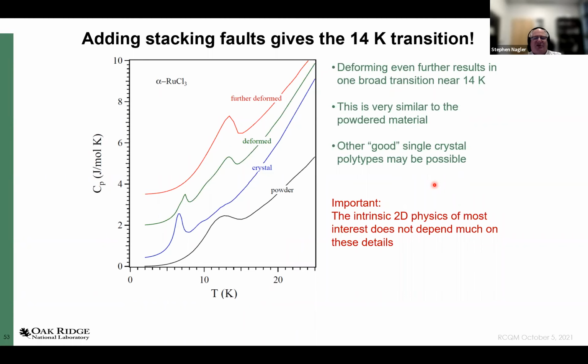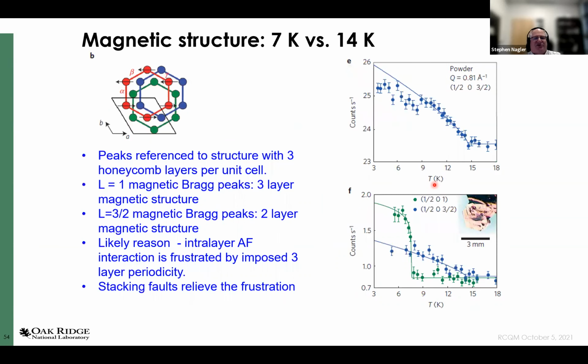Luckily, most of the interesting physics is two-dimensional, so it's not necessarily affected by this, but one has to realize that the magnetic structure is actually a 3-dimensional magnetic system with a 3-dimensional ordered structure, and it is affected by these stacking faults. In fact, the earliest crystals that we made had some amount of material with stacking faults in it, and they generally showed both transitions. The 7 Kelvin transition was pretty sharp, and it occurred at wave vectors with L equals 1. The 14 Kelvin transition was broader, and occurred at wave vectors with L equals 3/2.